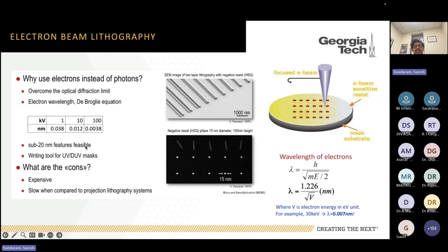Sub 20 nanometer features are feasible using this tool at lab scale. But in production scale, we use extreme UV lithography. If you use X-rays, you can reach much lower feature sizes also. That is possible. The cons are that it is very expensive. It is very slow. That's why it is not industrially compatible. Normally the exposure takes days. Sometimes it takes weeks to get 15 or 20 nanometer patterns.